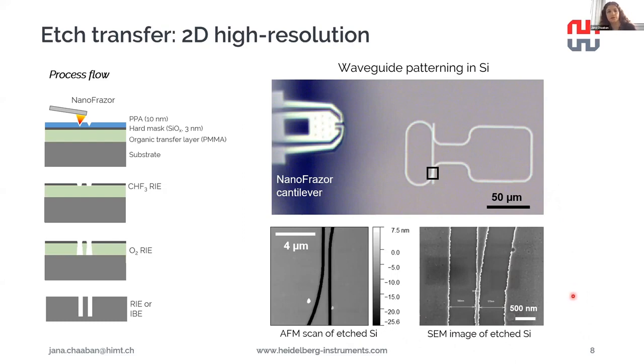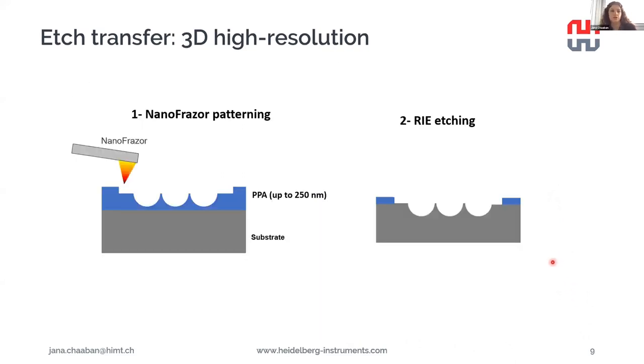Another thing we can do with our NanoFrazor technology, other than 2D transfers of patterns, we can also do multiple profile depth or so-called grayscale lithography transfer. And this is shown here. In this case, we can also just use one thick layer of this thermally responsive resist PPA. And with our cantilever tip, we can go as deep as 250 nanometers. And we can very accurately tune the depth profile here and transfer it with a dry etching step into the material of choice. So one prominent example is transferring such a pattern into silicon.